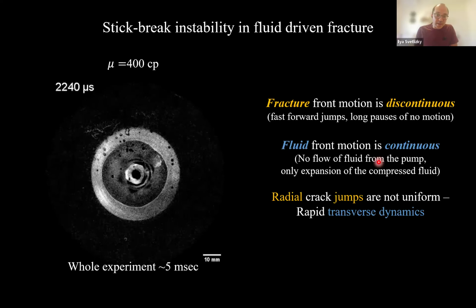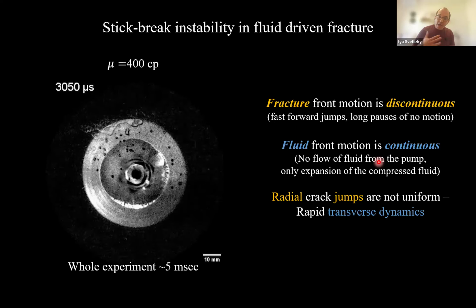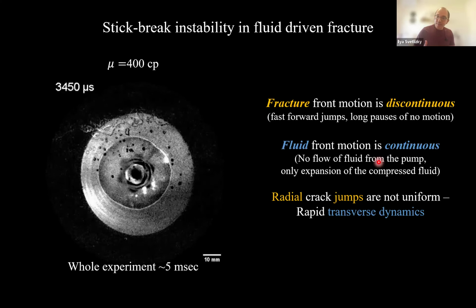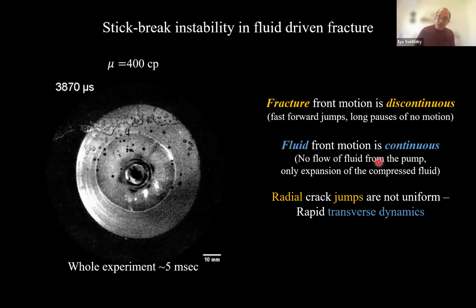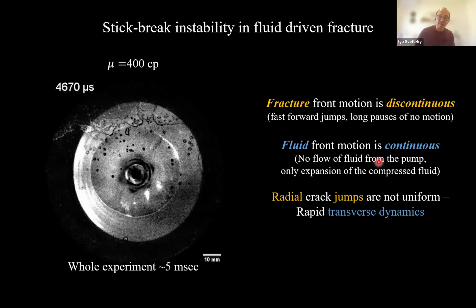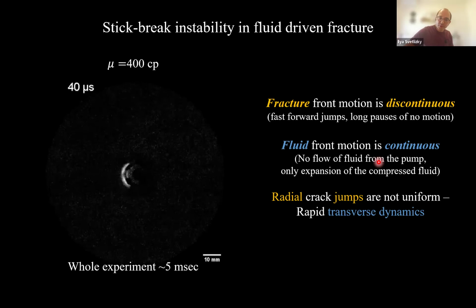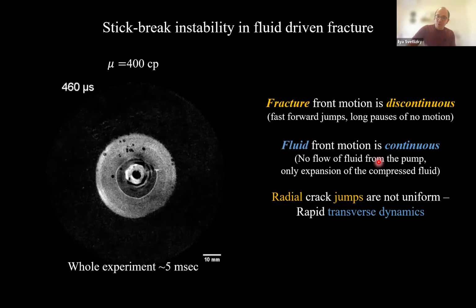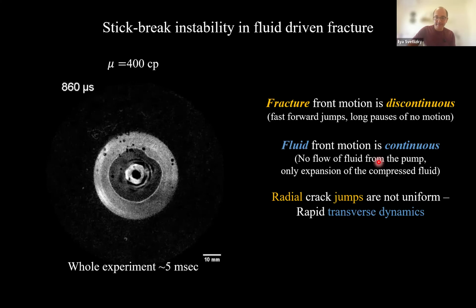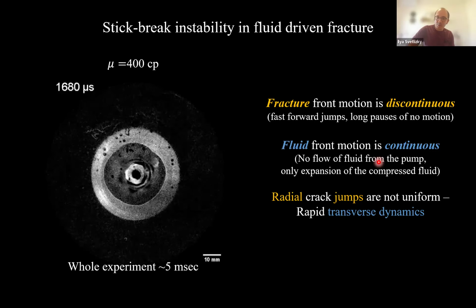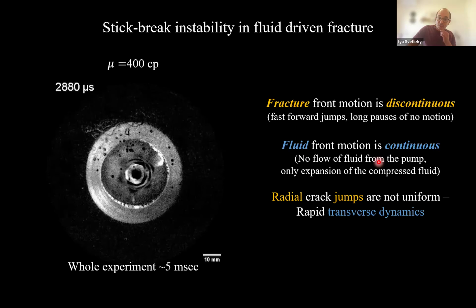And the third thing, which is the most interesting in our opinion, is that the radial expansion of the crack doesn't take place uniformly. Rather, it nucleates at some point and then expands in a transverse direction extremely fast. Okay, so these are the three observations that I want you to keep in mind. And the rest of the talk, all I'm going to do is to try to convert these nice movies into science, okay? Just to provide some detailed analysis of what you see on the screen.